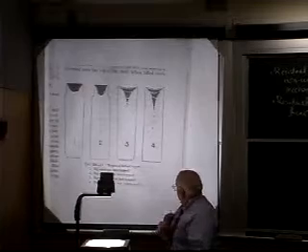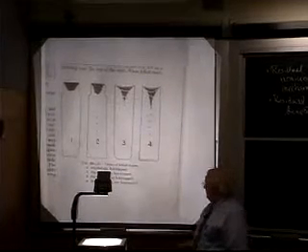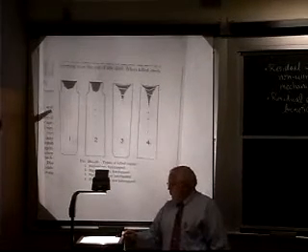of typical ingot casting technology, which they still do a little bit of. About 2% of the steel is produced this way. All of the aluminum in the world is produced this way. This is ingot casting. And you have slightly tapered walls.